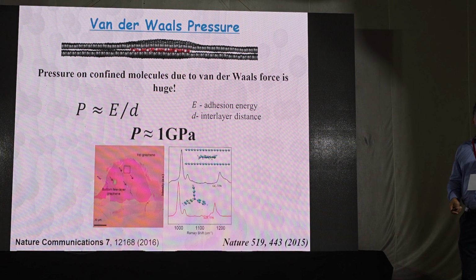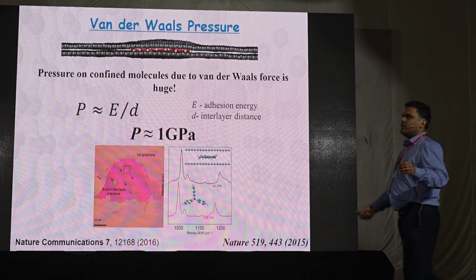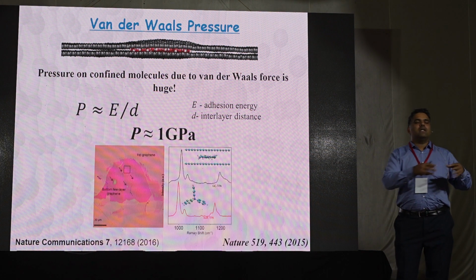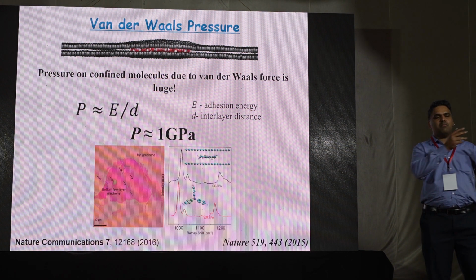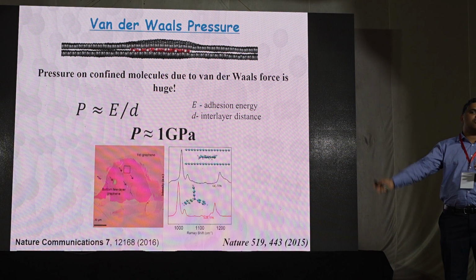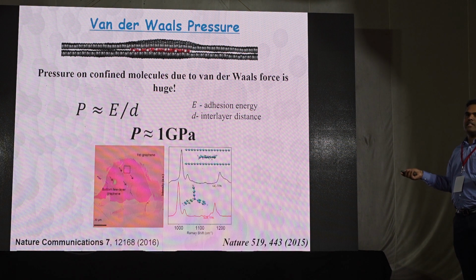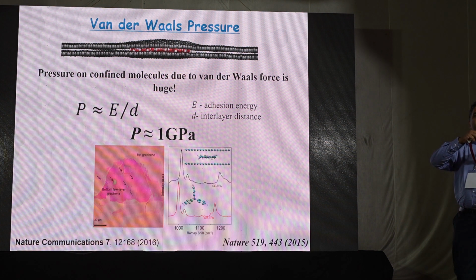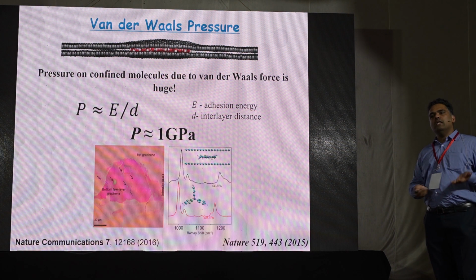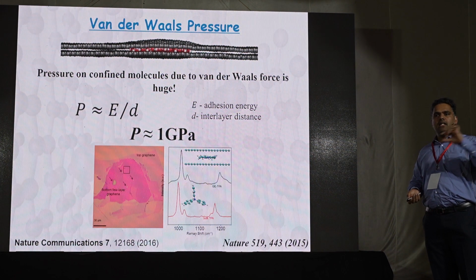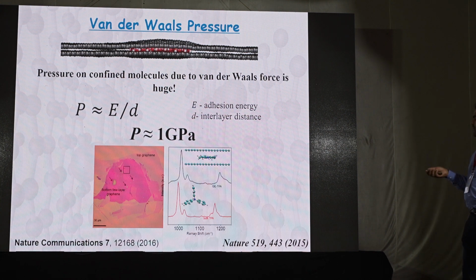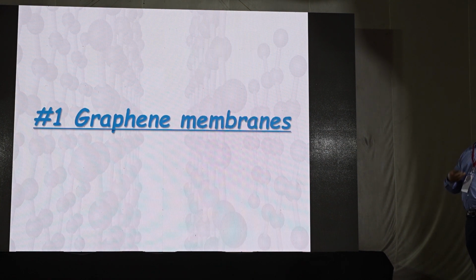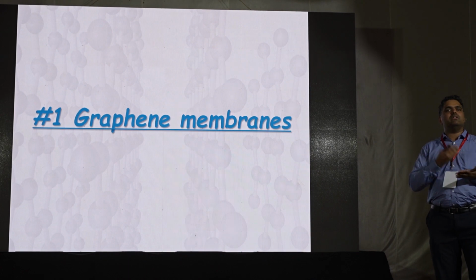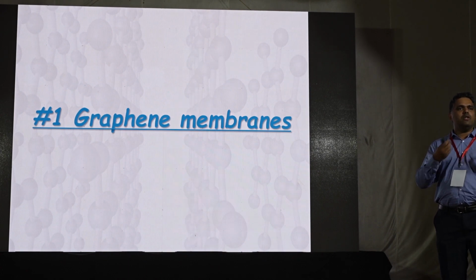An example is magnesium chloride. Any chemist knows that if you take magnesium chloride and put it in a hydrothermal reaction, like a pressure cooker, it gets converted into magnesium oxide. The same reaction without any temperature can happen between two graphene layers. If you put magnesium chloride between graphene layers and characterize it, you find that it is a layered magnesium oxide. It's again a thin layer of magnesium oxide. So this is an example I wanted to show. We can do different types of chemical reactions even in between the layers, and that opens up very new chemistry